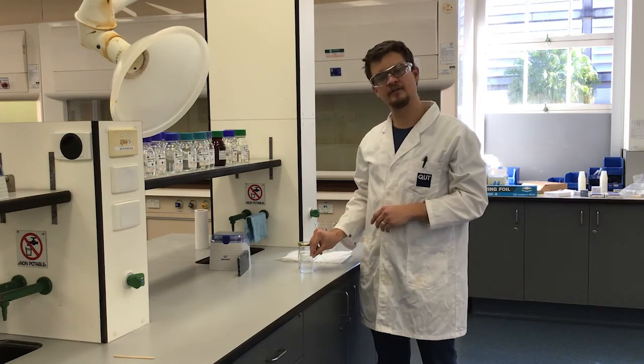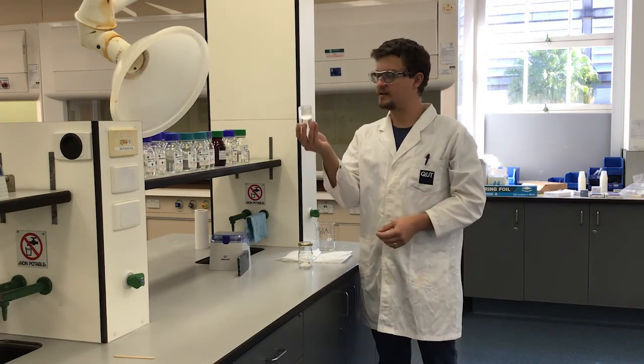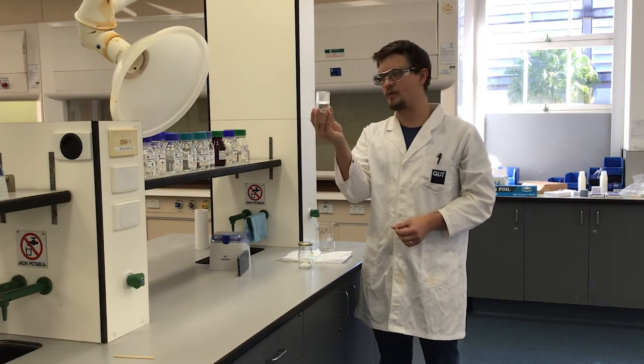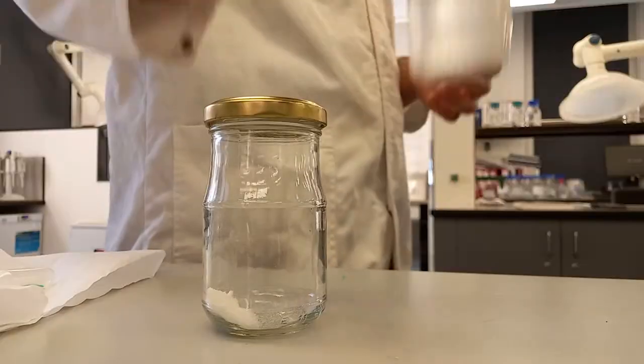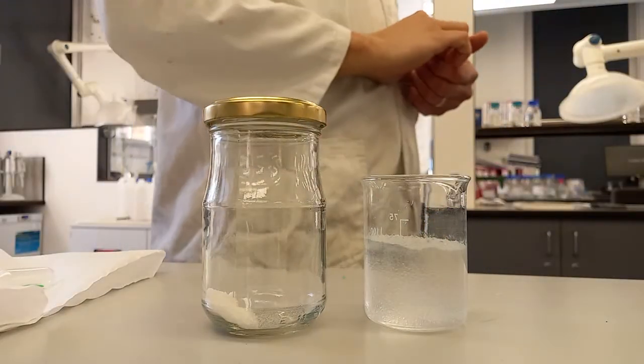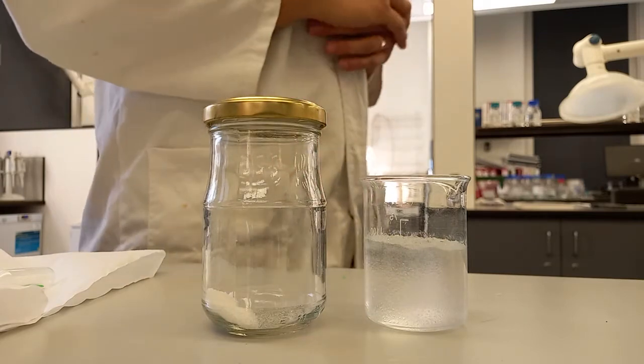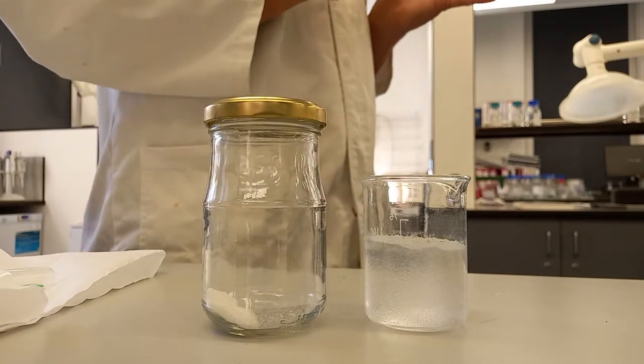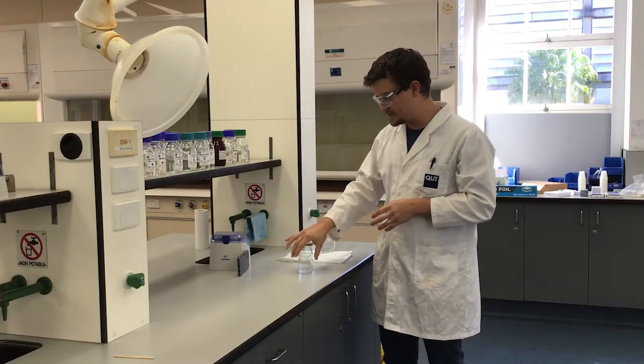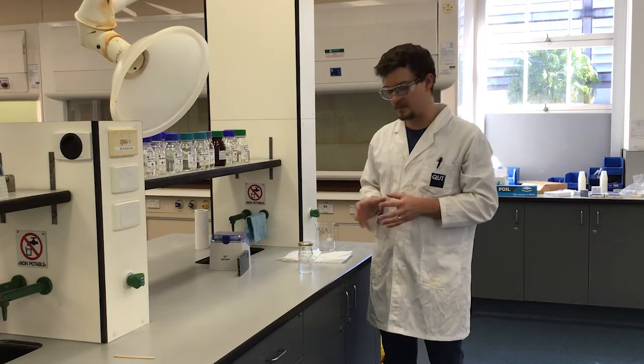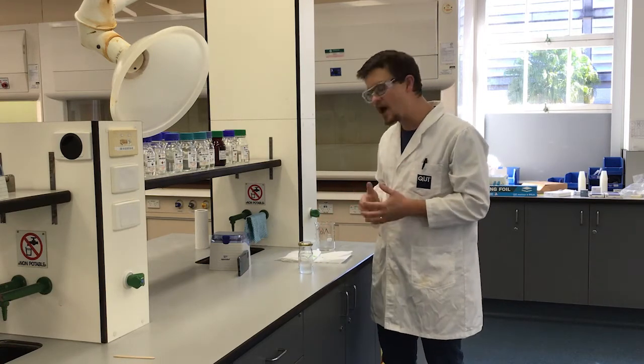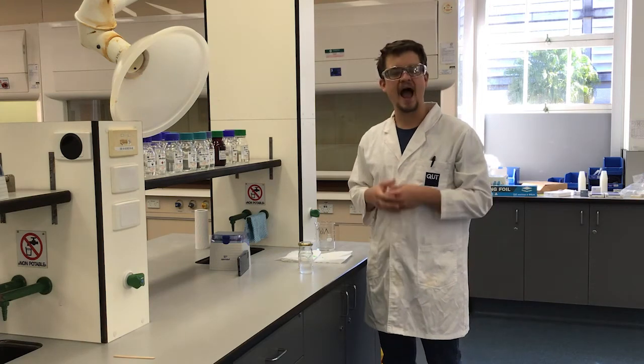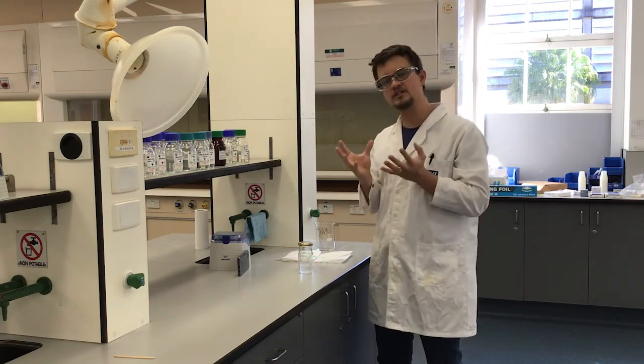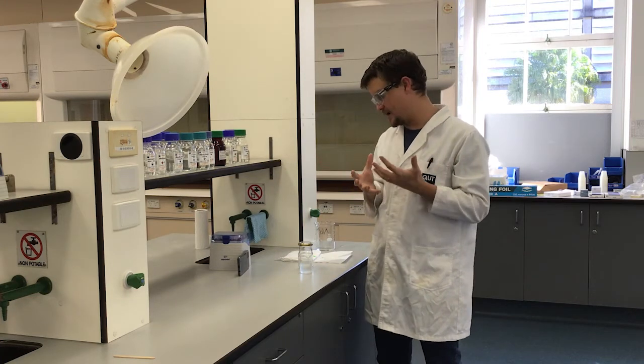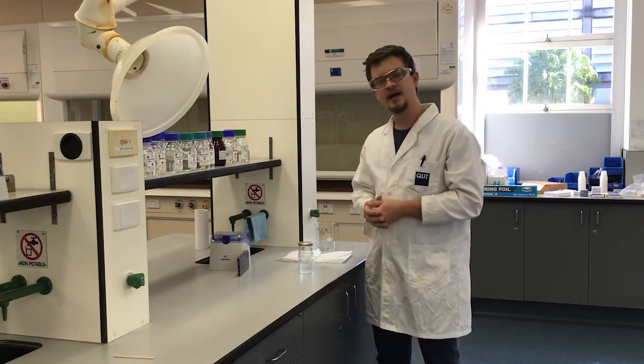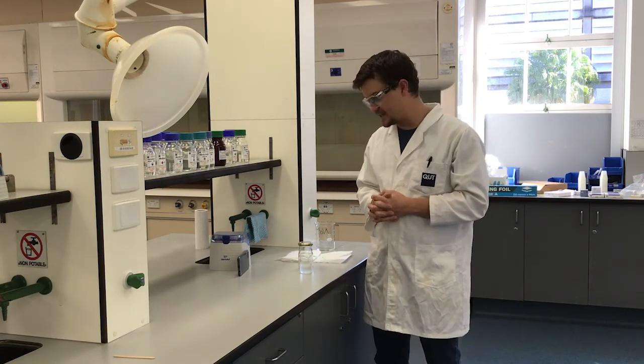That's pretty amazing stuff. Very quickly, we can see that the sodium polyacrylate has soaked up all of that water and has formed a gel-like material. So I said that I put 0.5 gram of sodium polyacrylate in here, and I've added about 50 milliliters or 50 grams of water. That means that in this beaker, only 1% of the material in there is actually polymer, and 99% of that is water. And that's typically the definition of a hydrogel, is that very small amounts of solid make up the network, and it's mostly water.